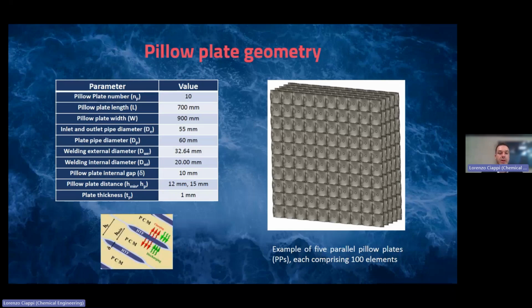Reducing the distance between two adjacent pillow plates reduces the time that is required for melting and solidifying the phase change material. However, during the design process, it's important to evaluate this parameter because it can pose constraints in the manufacturing process. In this case, it was considered a minimum distance of 12 millimeters and a maximum distance of 15 millimeters, while the internal gap inside the pillow plate is 10 millimeters.